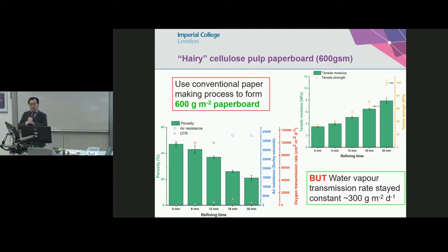Now, it all sounds good on paper, but in reality, this thing is still not quite resistant to water. Again, remember, cellulosic molecules, cellulose themselves, are actually hygroscopic. So water loves it. We haven't actually had a very good way to stop water from passing through, but it's already a good start on reducing the oxygen transmission through these structures.